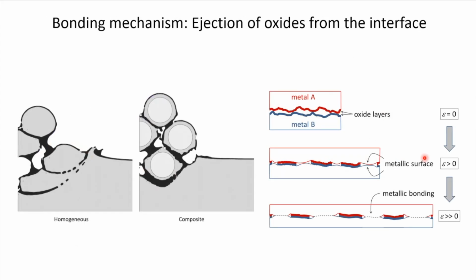But everything that we said tells you where or how you should expect bonding, but it doesn't tell you anything about the mechanism of bonding. On the mechanism, the common notion so far is that metallic particles form a thin layer of oxide on the surface, and that will not allow perfect bonding. So the main role of interfacial deformation is to get rid of those oxides, either by ejecting them from the interface or making some spaces between the oxides by rupturing them. That's probably the main mechanism for metals, but for other materials, I think it's still under development, and we don't know exactly how it works for instance for ceramics. So the lesson here was to differentiate between what is called a mechanism and what is regarded as a criterion. This shear instability should probably be regarded as a criterion more than a mechanism.